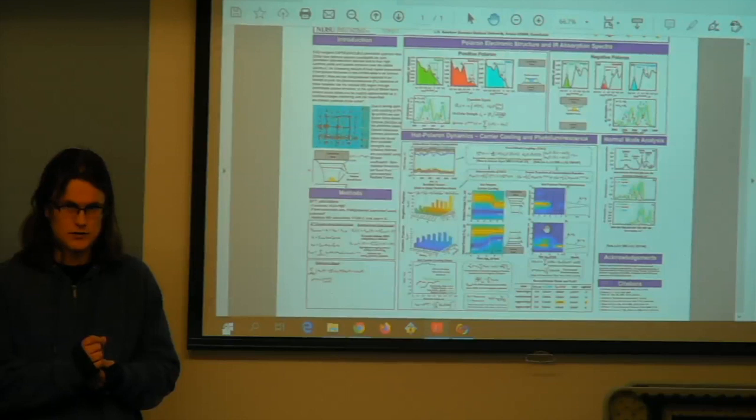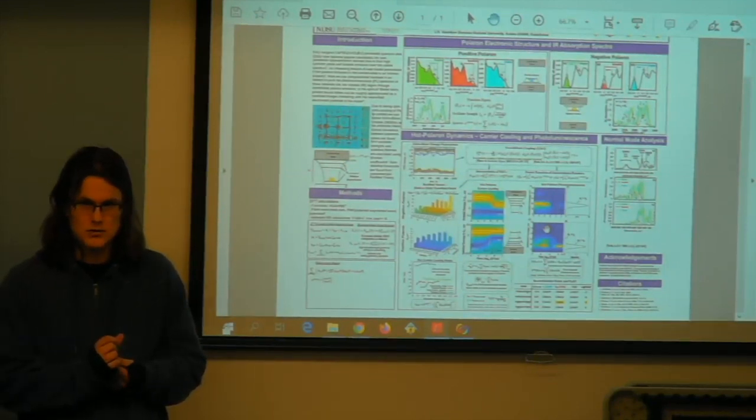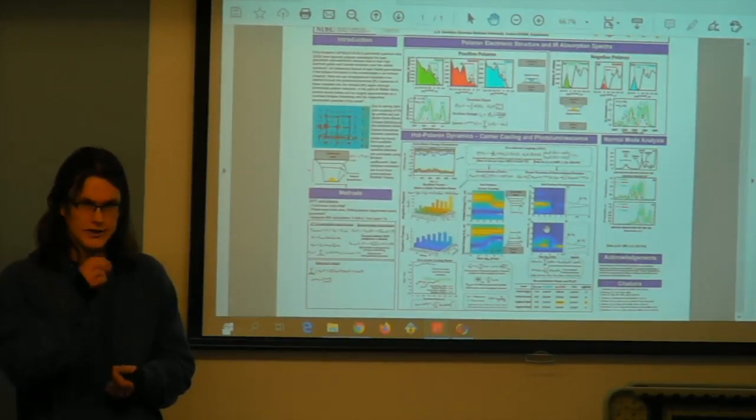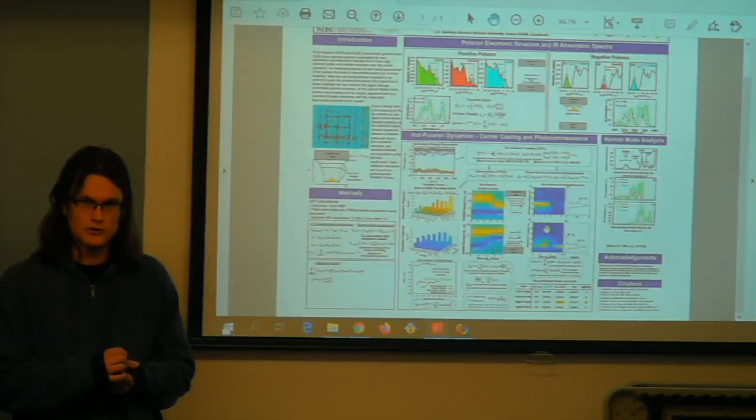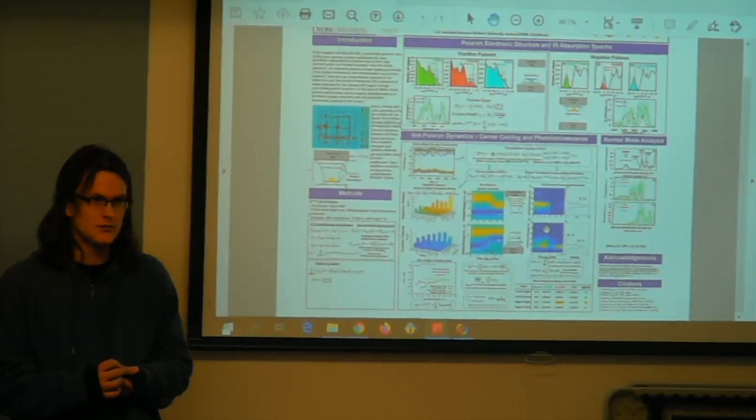Has this been applied to a system that has an experimentally determined quantum yield, so you can get quantitative agreement versus qualitative? Right. If you just consider interband photoluminescence, across the band gap, you computed that it is like 60%. And is that comparable? Yeah, in experiment they see anywhere from 50 to 100.